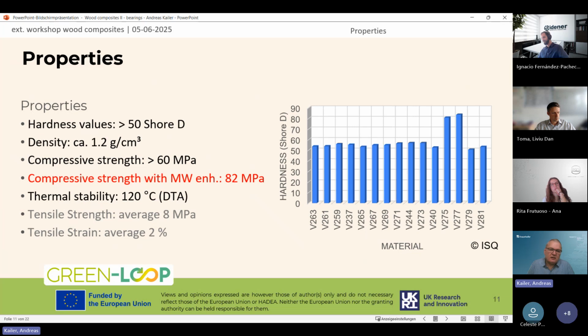Not so good was, as expected, tensile strength of a bit lower than 10 megapascals, which is but no problem for tribology, for our application in tribology. And the tensile strain is also rather small here at this point.